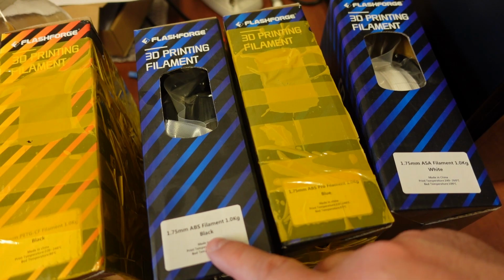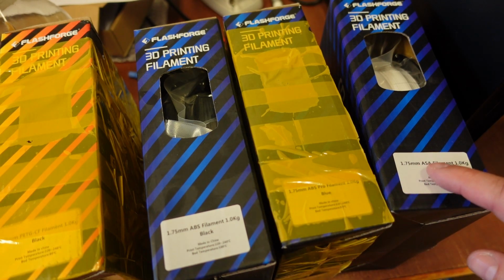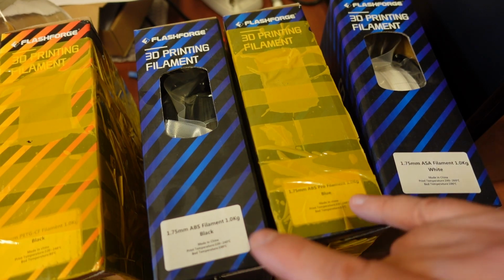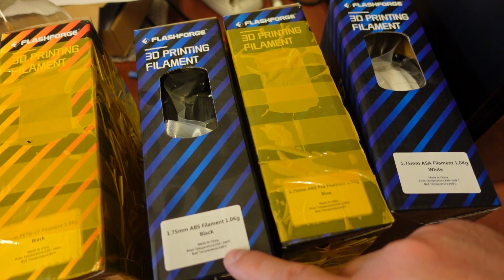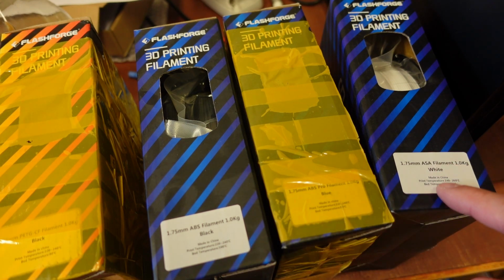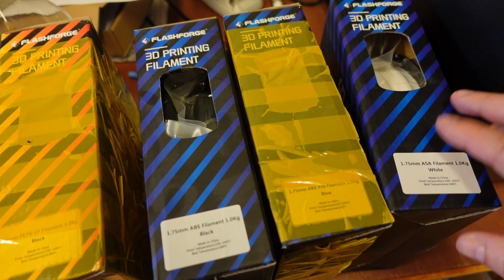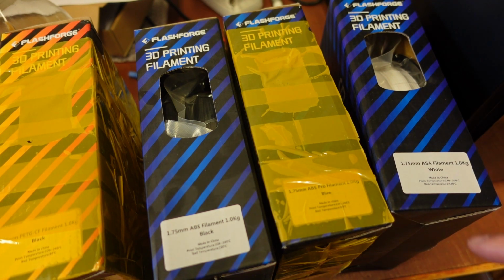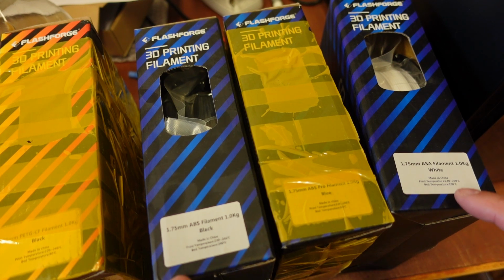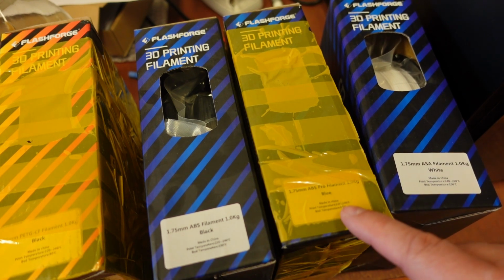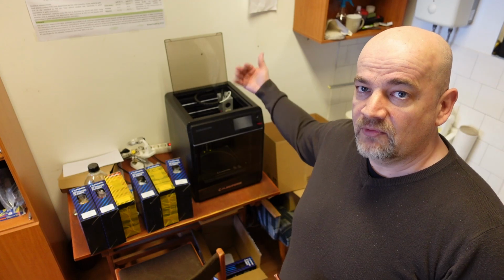This is ABS filament in black color, ABS Pro in blue color, and ASA in white color. We have some information on the box: the print temperature for both ABS filaments is between 220 and 240 degrees Celsius, and the ASA is between 240 and 260 degrees Celsius, so a little bit higher. On the bed temperature, I also can see some difference: for ABS and ASA 100 degrees Celsius, for ABS Pro 80 degrees Celsius. Everything will be printed on the Adventurer 5 Pro 3D printer, which is enclosed, and this is important for these filaments, as it will reduce the warping. And everything will be printed with a 0.4mm regular brass nozzle.